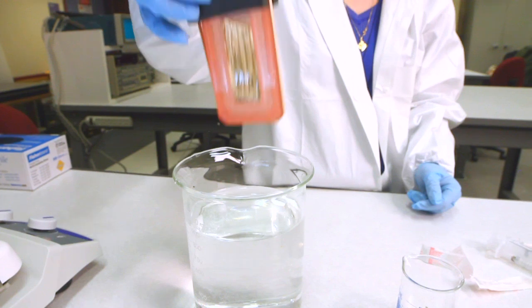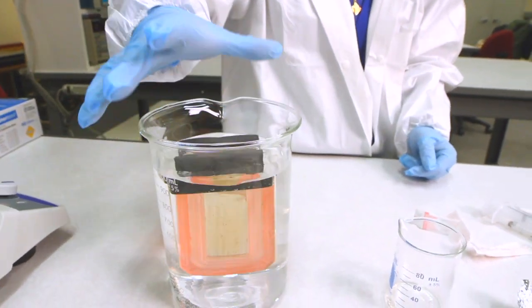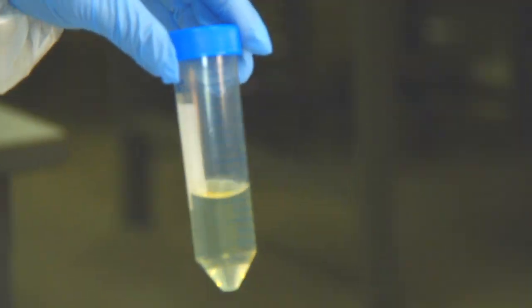We now have a solution of the silk with the salt, which we then dialyze to remove all of the salt. And then you're left with just a pure water solution of the silk protein.